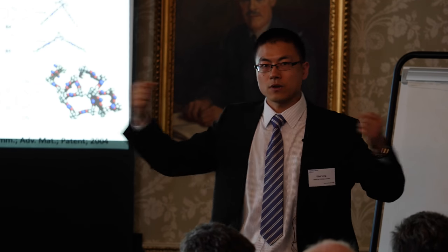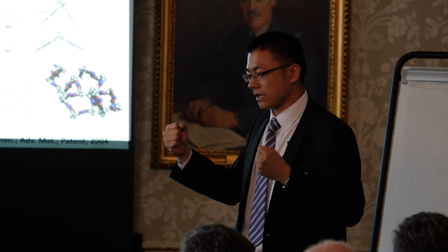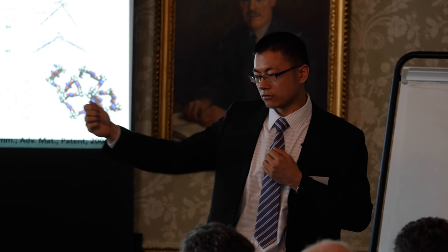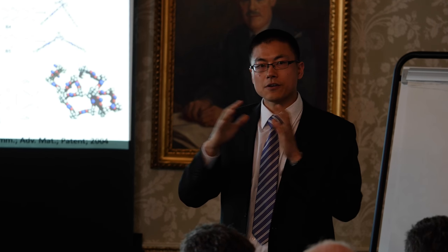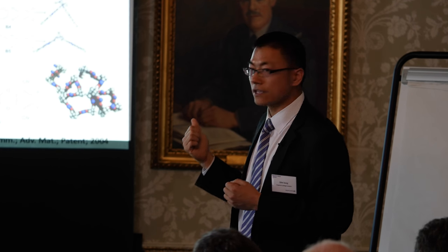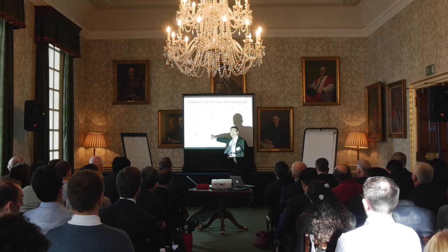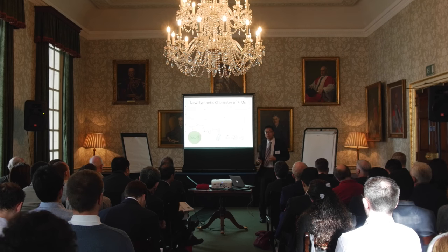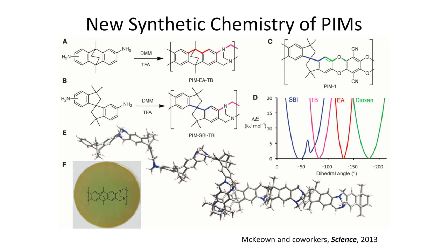The polymer chain is a long molecule — like noodles — made of different building blocks linked together. Conventional polymers are very flat molecules. PIMs are synthesised using rigid, contorted monomers: when you link them, you incorporate angles into the polymer chain, forming contorted molecules. The chemistry of these molecules is very versatile. Recently, for example, Neil McKeown's group developed a new TB polymer that gives a very rigid, ladder-like polymer.